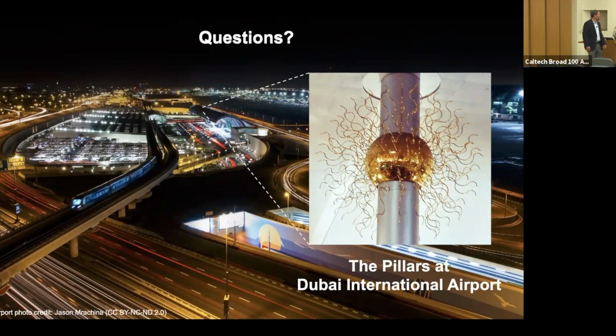Okay, here's a question from a different category. Once they're formed, can the SNA lattices be dried and retain their lattice structure? And can they be exposed to non-optical irradiation, for example ultrasound waves, and exhibit some sort of resonance properties? So the answer is, in the as-made way, in solution, if you dry them, the oligonucleotides will just compress and fall onto the surface, and you lose most of the structure. But if you lock them into place using the silver ion trick or the silica, then you can do almost all of the above.